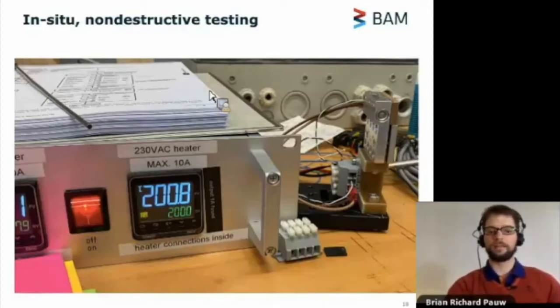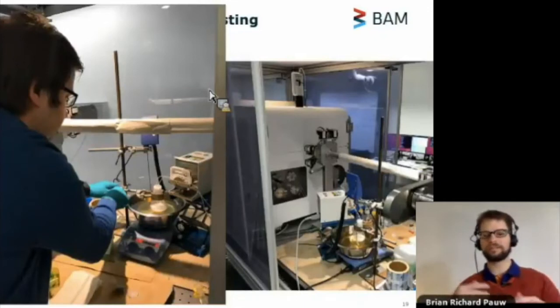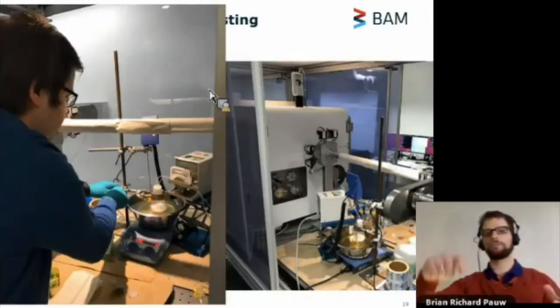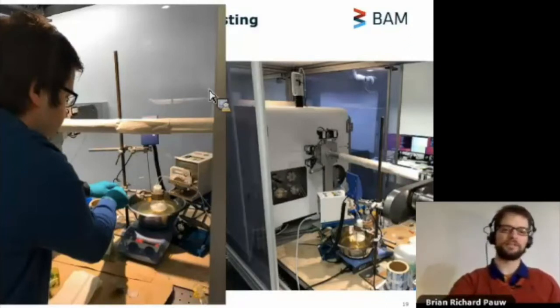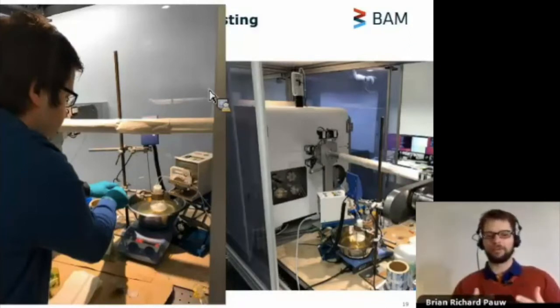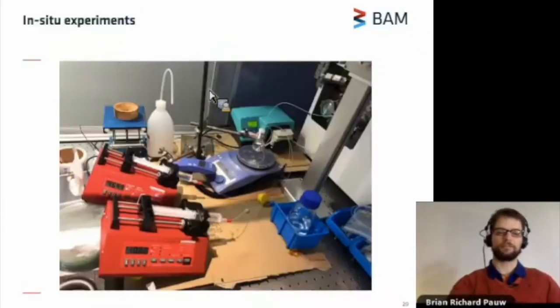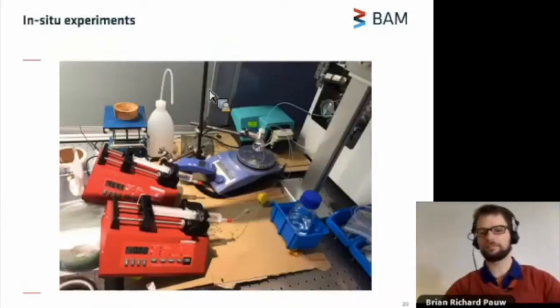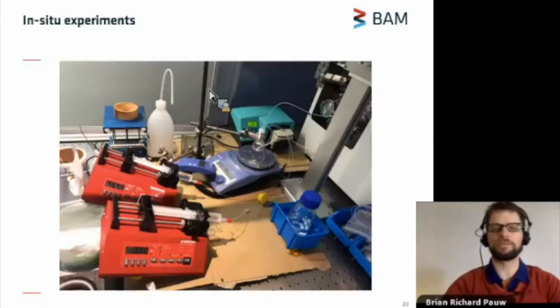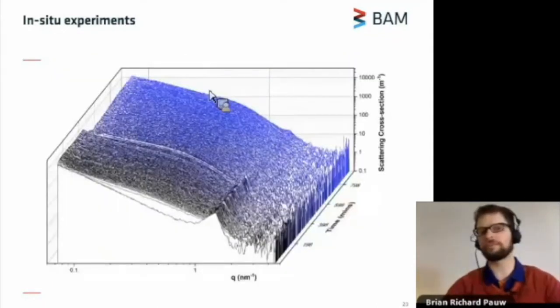Another thing we can do is we can do chemical reactions next to the instruments. So you can do a lab scale chemical reaction and pump a little bit of that liquid through our machine. And that means that we can observe the structural changes in the sample during the synthesis. We can collect scattering patterns with a practical time resolution of about 10 minutes.